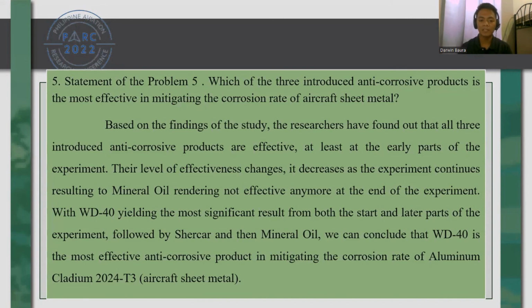Statement of the problem 5 asks, which of the three introduced anti-corrosive products is the most effective in mitigating the corrosion rate of aircraft sheet metal? Based on the findings of our study, we have found out that all three introduced anti-corrosive products are effective, at least at the early parts of the experiment. Their level of effectiveness decreases as the experiment continues, resulting in mineral oil being not effective anymore at the end of the experiment. With WD-40 yielding the most significant results from both the start and later parts of the experiment, followed by Shercar and then mineral oil, we can conclude that WD-40 is the most effective anti-corrosive product in mitigating the corrosion rate of aluminum Cladium 2024-T3 or aircraft sheet metal.